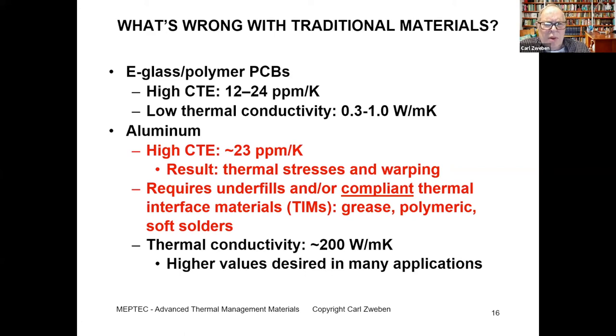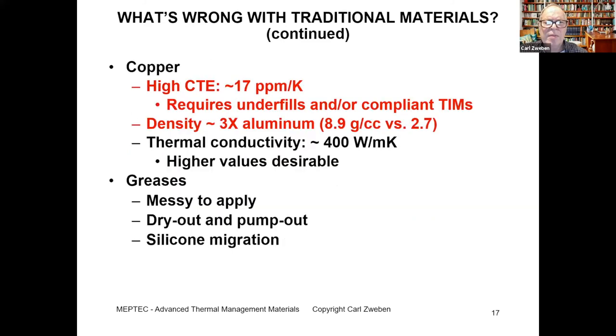The main problem with aluminum for packaging is that it has a high CTE, 23 parts per million per degree Kelvin. The result is thermal stresses and warping, and it requires the use of underfills and/or compliant thermal interface materials, which we call TIMs, such as greases, polymeric TIMs, and soft solders. Aluminum has a pretty good thermal conductivity, 200 watts per meter Kelvin, but we certainly would prefer higher values in many applications. We look at copper, the main problem is the high CTE combined with high density, 8.9 grams per cubic centimeter, which is about 3 times that of aluminum.